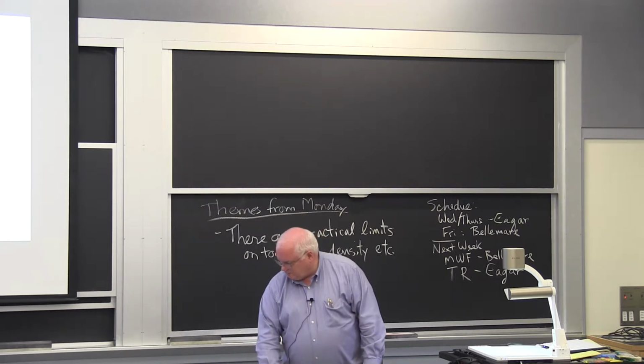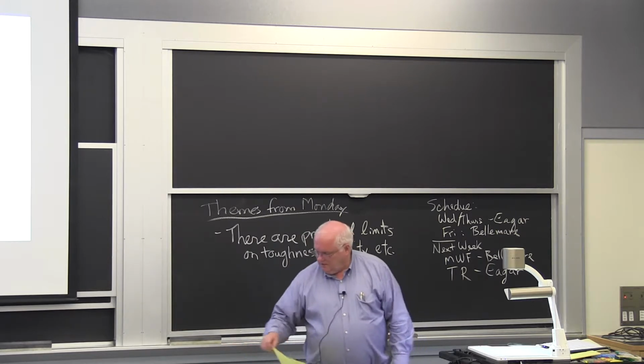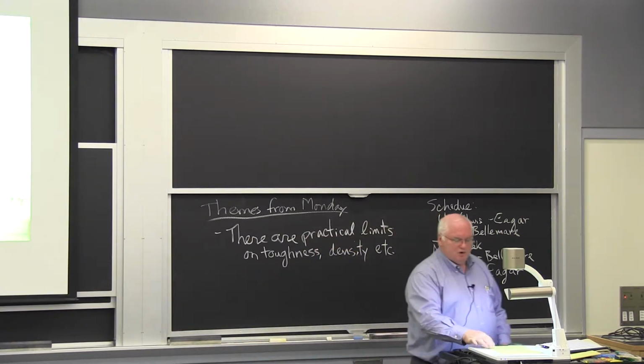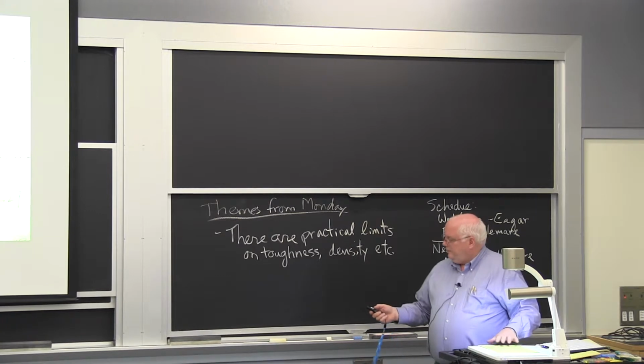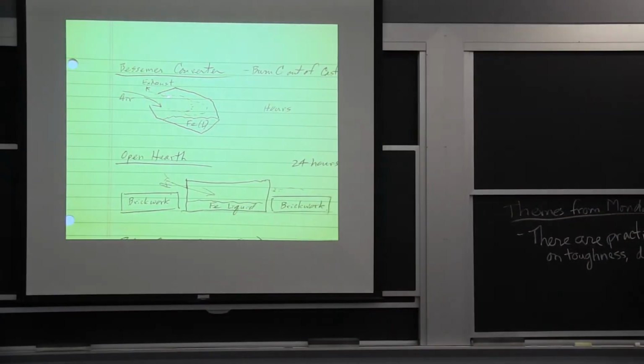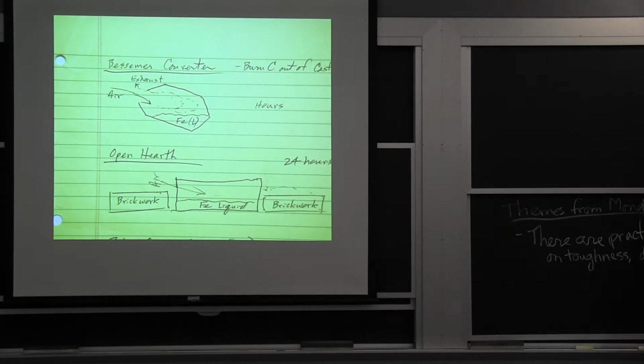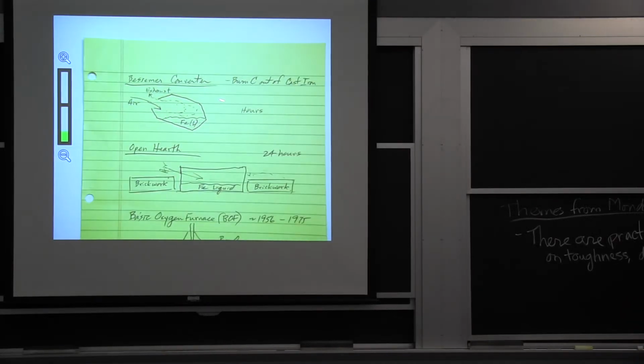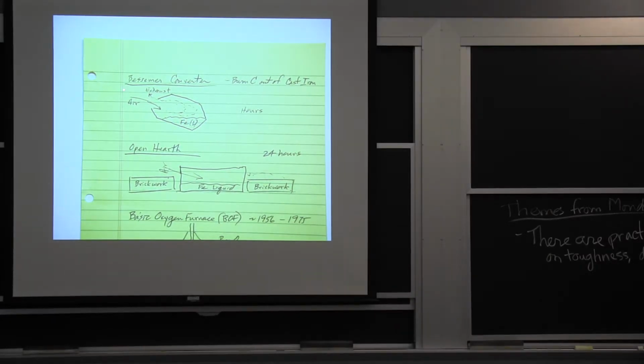And then we talked about the nails. Well, let's talk about what happened in some of these processes. So the Bessemer converter came along, and what happened is you couldn't melt steel with a regular fire. You can stick a poker of steel or even cast iron in a hydrocarbon fire burning in air, and we make furnace tools. Okay, we make the hearth and stuff out of cast iron. Okay, it doesn't melt. But Bessemer came along, and basically what he did is he built a converter where you had the liquid iron here and you'd blow the air in, but the exhausting air would come out and it would sort of preheat the air coming in.